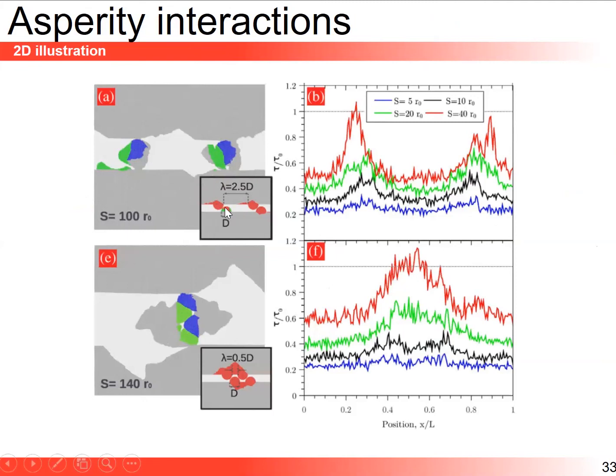Okay. And we can see this in those simple 2D atomistic simulations, where look at this inset where we have 2 contacts occurring in those red regions. And if you shear the system, you see you start to develop shear stress beneath the surface, tau, that develops two peaks in red here at the two disjoint contacts. And because both of them have maybe a junction size larger than this d star, you form two debris. So that's a later time in the history, you have formed two debris particles. However, if you reduce the space between those asperities, lambda is the spacing, and you bring them very close together, then you realize that you form a single debris that has a larger volume than a combined single debris. And that's because there's elastic interaction. You see a single peak in the stress field underneath the surface.